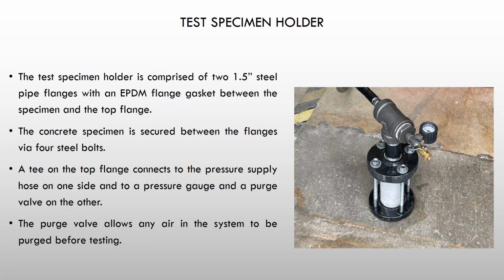The test specimen holder is comprised of two 1.5-inch steel pipe flanges with an EPDM flange gasket between the specimen and the top flange. The concrete specimen is secured between the two flanges via 4 steel bolts. The T on the top connects the pressure supply hose, which is right here, to a pressure gauge and a purge valve. The purge valve is there to let any air out that's in the system before the testing commences.